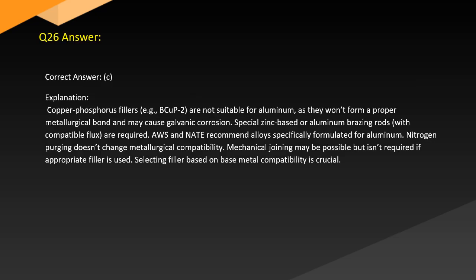Answer. Correct answer: C. Explanation. Copper phosphorus fillers, e.g. BCuP-2, are not suitable for aluminum as they won't form a proper metallurgical bond and may cause galvanic corrosion. Special zinc-based or aluminum brazing rods with compatible flux are required. Manufacturers recommend alloys specifically formulated for aluminum. Nitrogen purging doesn't change metallurgical compatibility. Mechanical joining may be possible but isn't required if appropriate filler is used. Selecting filler based on base metal compatibility is crucial.